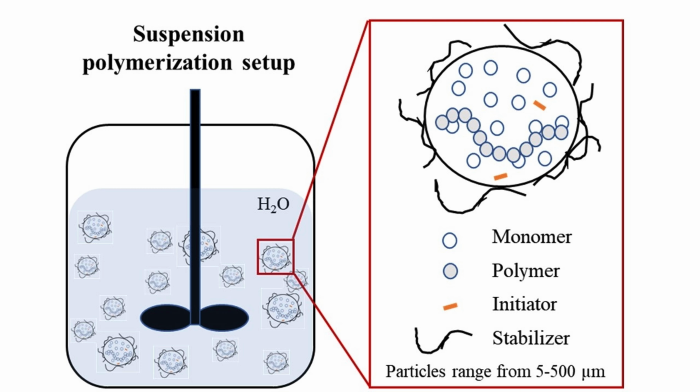Drop stability depends largely on the nature of the drop stabilizer or suspending agent. Water-miscible polymers, both naturally occurring and synthetic, are often used as drop stabilizers. Polyvinyl alcohol, gelatin, starch, and methyl cellulose are used to stabilize the droplets and prevent coagulation.